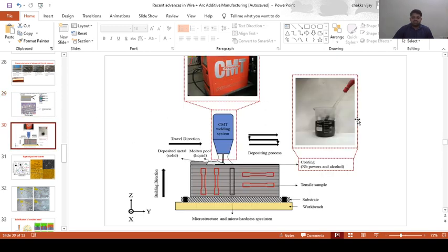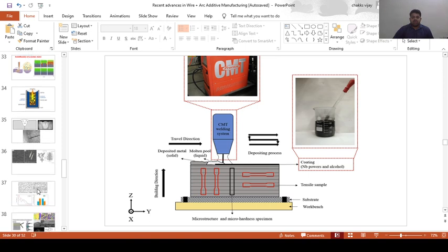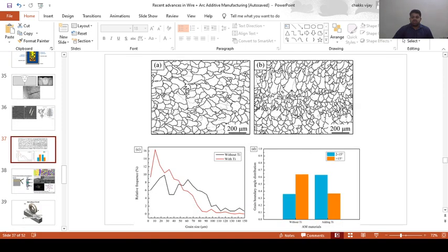Whenever we use a niobium coating or something else at the end of each layer deposition, you can avoid this kind of coarsening effect. Here you can observe a fine grain configuration at the interface area. So this is the interface. In the interface also, only coarser grain is there without titanium powder.